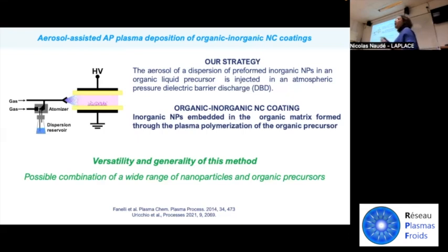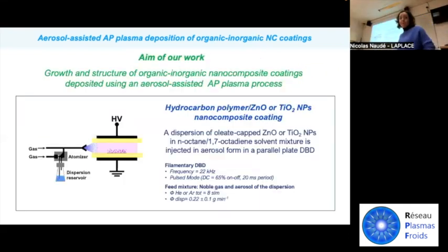That is, we need a certain chemical compatibility to obtain a dispersion of good quality, depending on the application, that can be injected in the plasma. In 2014, we started to investigate the growth and structure of organic-inorganic nanocomposite coatings deposited by aerosol-assisted plasma processes. We use a classical parallel plate DBD reactor with a lateral gas injection of the feed mixture in the inter-electrode zone. We mainly focused on a very simple system, that is hydrocarbon polymer, metal oxide nanoparticles nanocomposite coatings. The particles we use are zinc oxide and titanium dioxide nanoparticles.